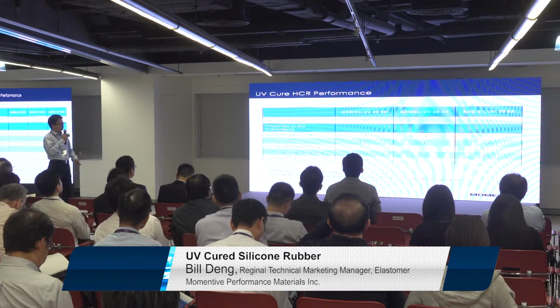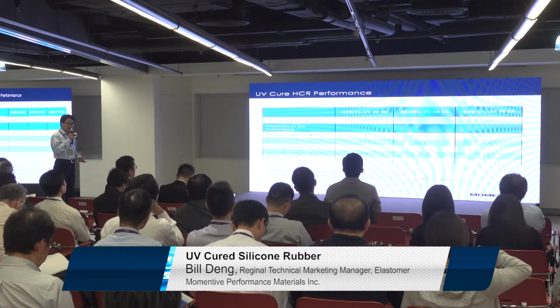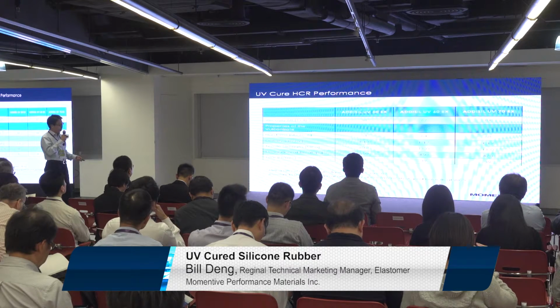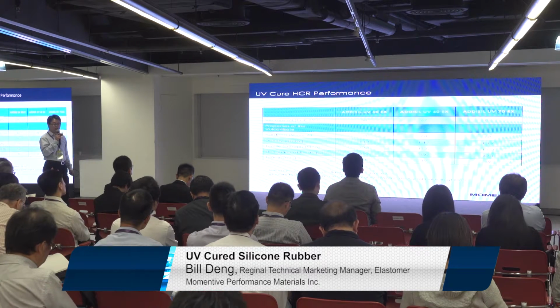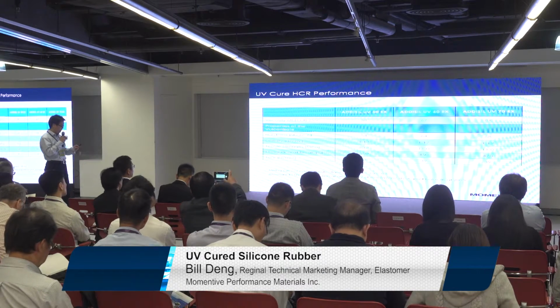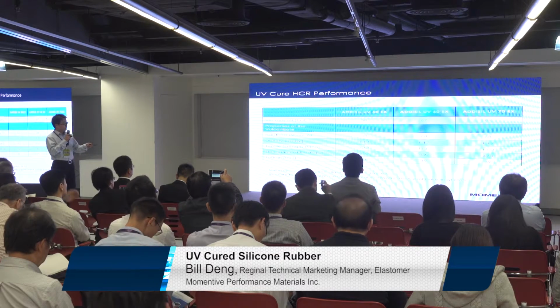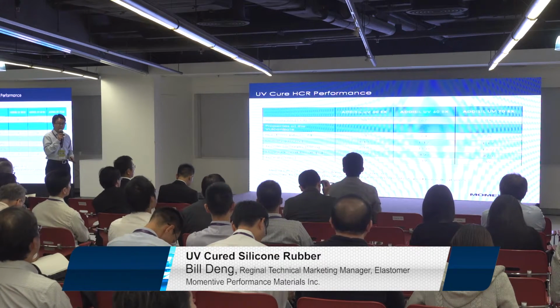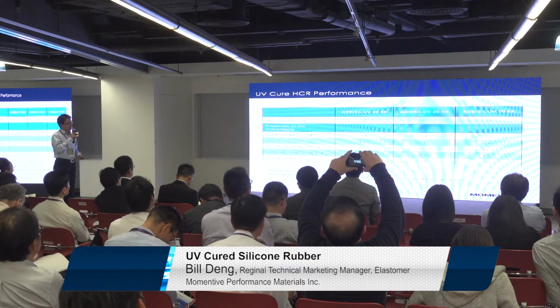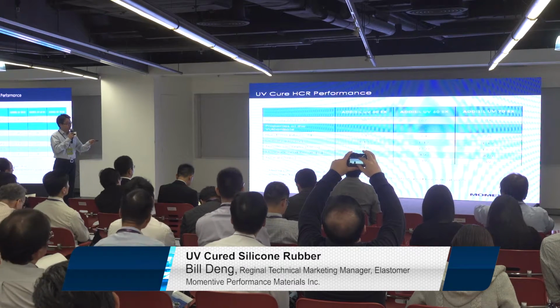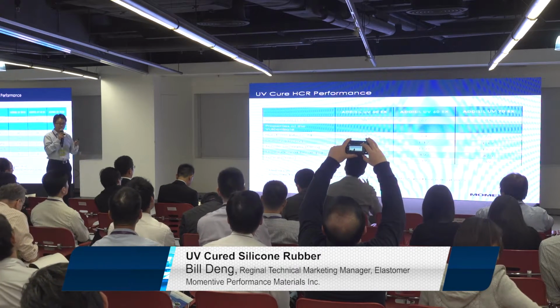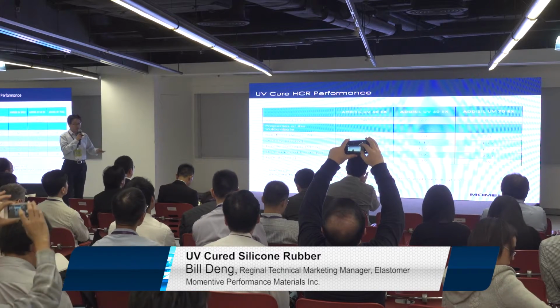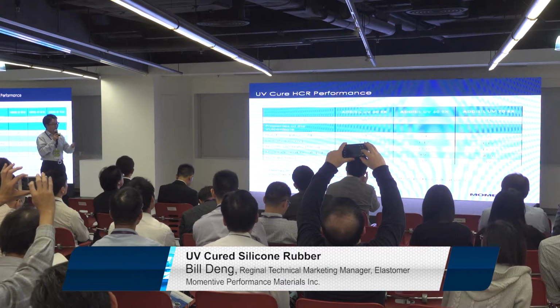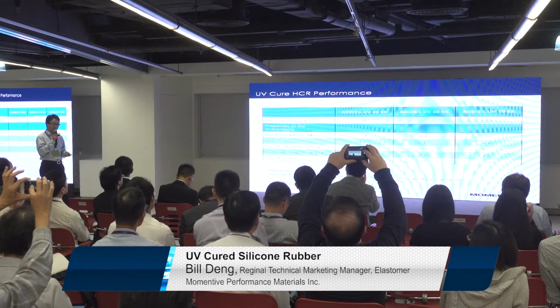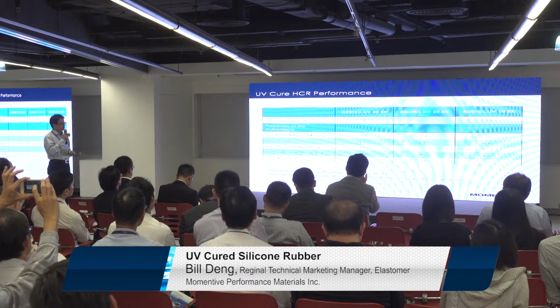We also have 3 different grades for the UV cured HCR for tubing and extruding. So we have 50, 60, 70 Shore A hardness. Usually 50 and 60 are mainly focused on medical tubing, and 70 is used for cable because of the high hardness and very, very stiff strength.